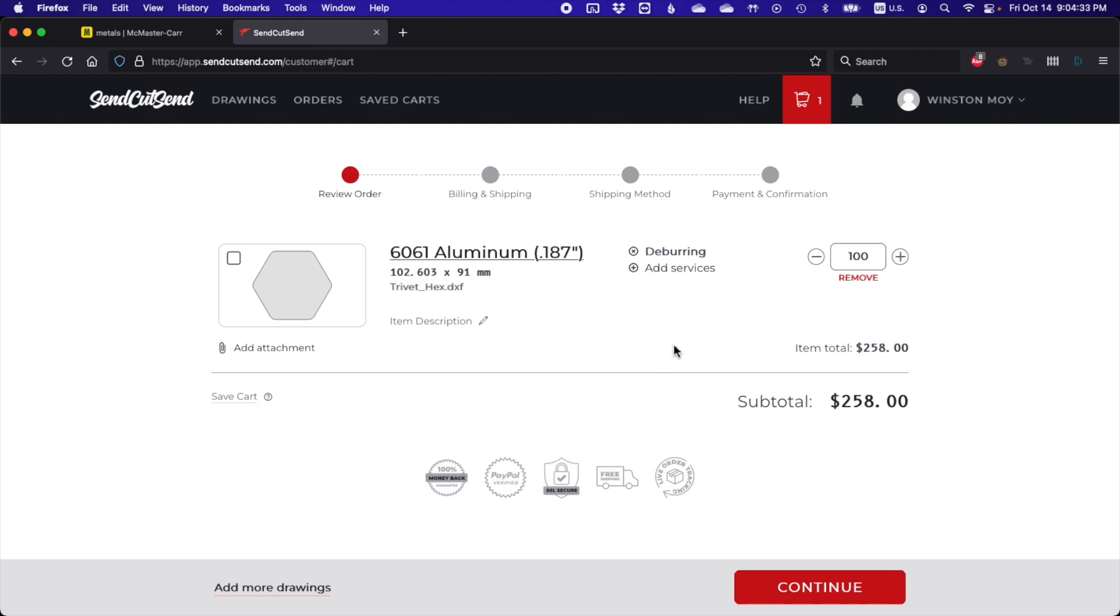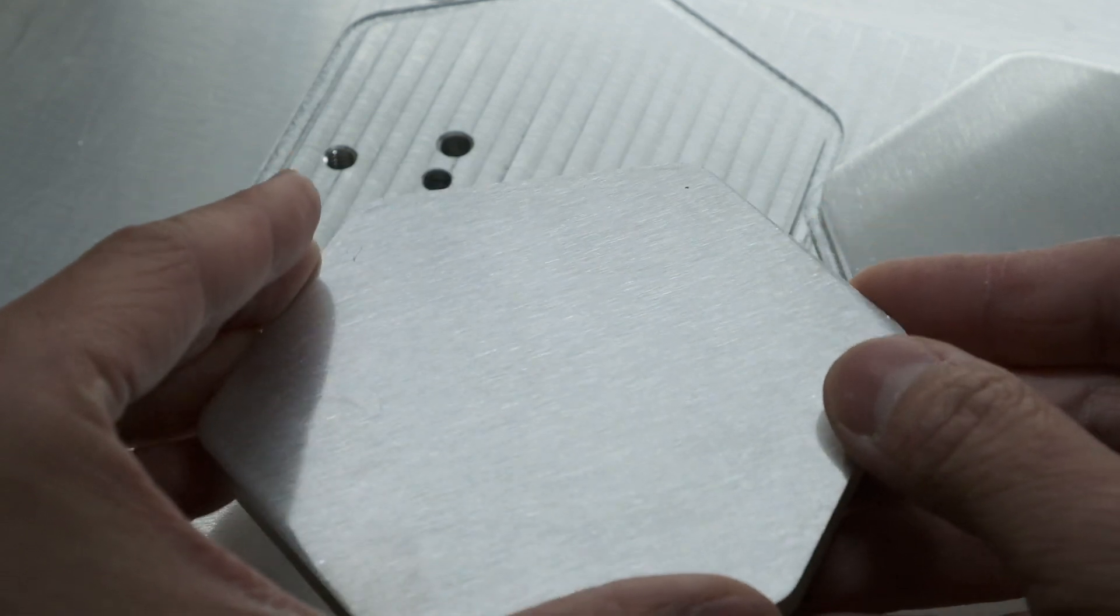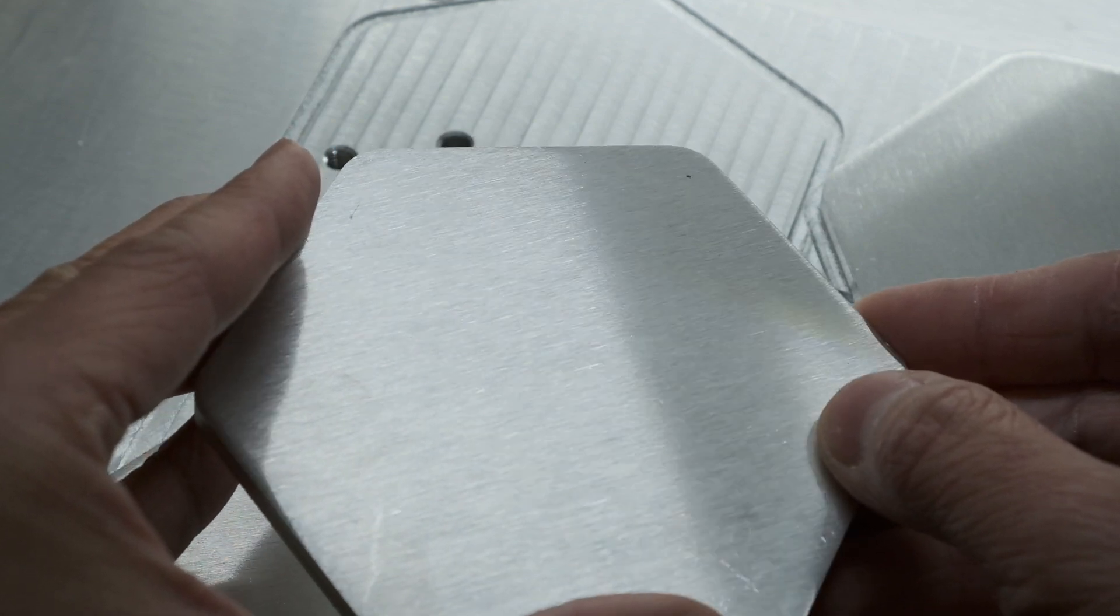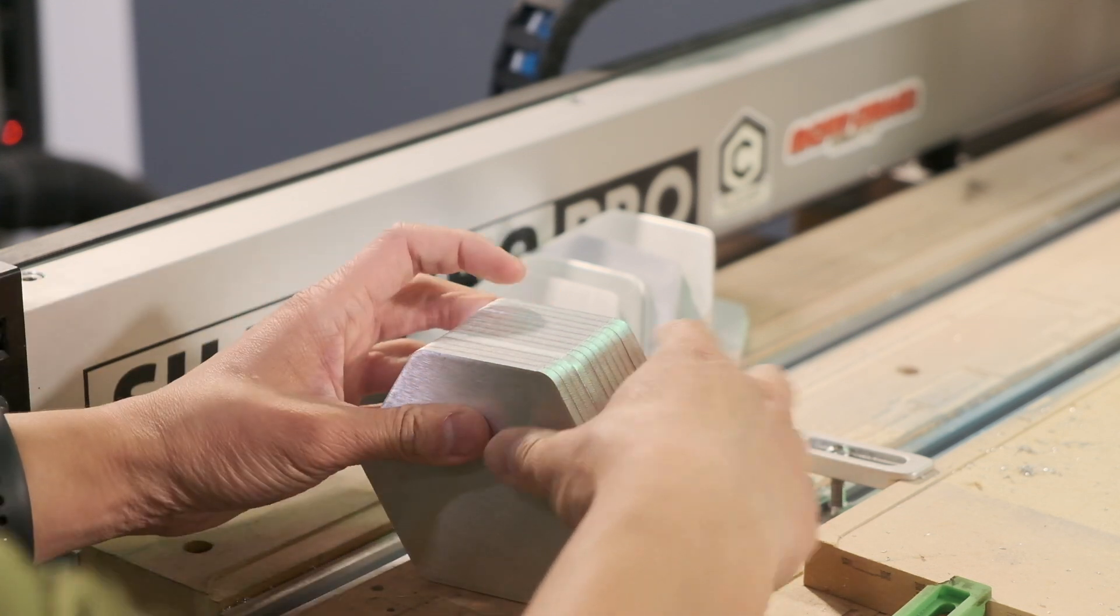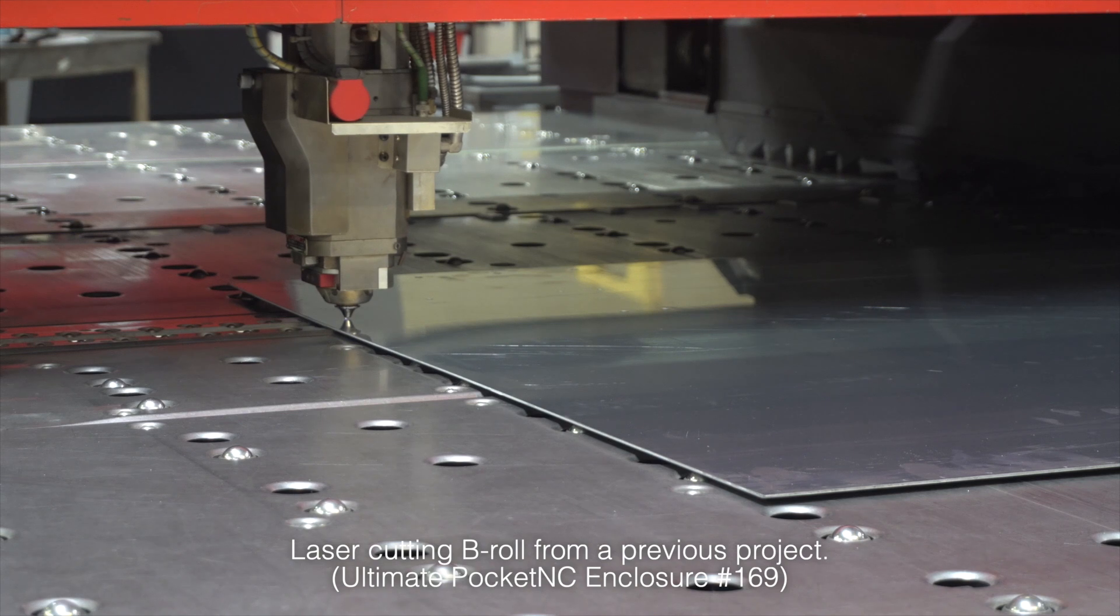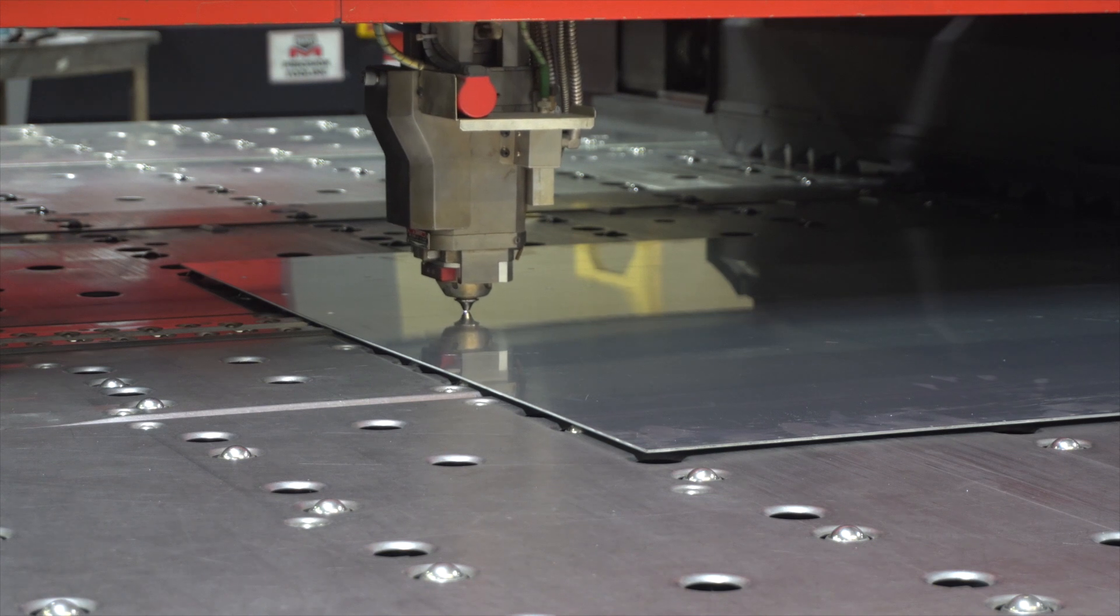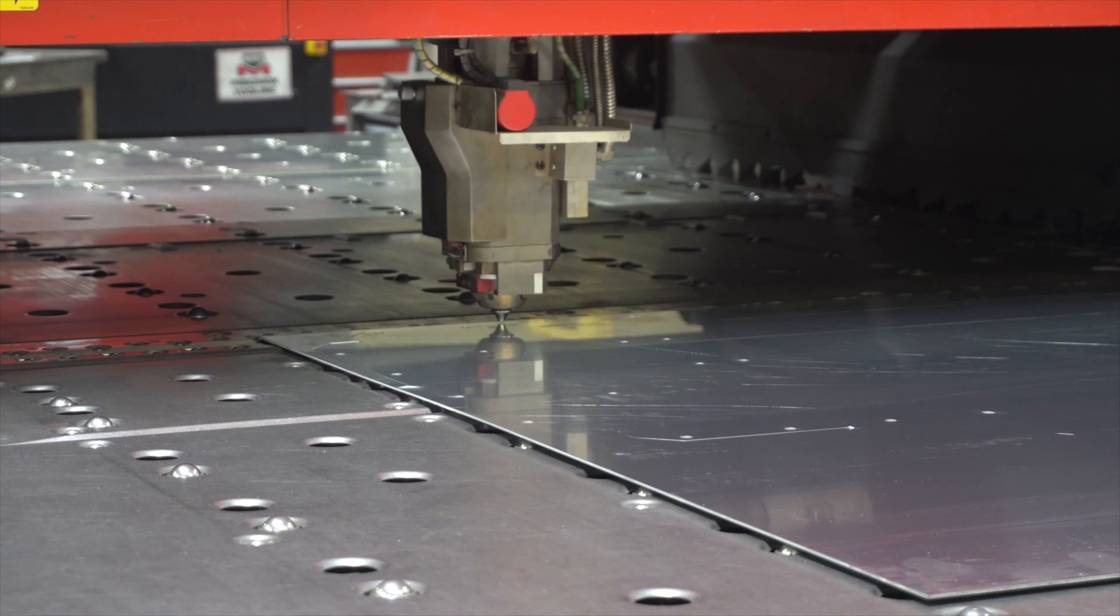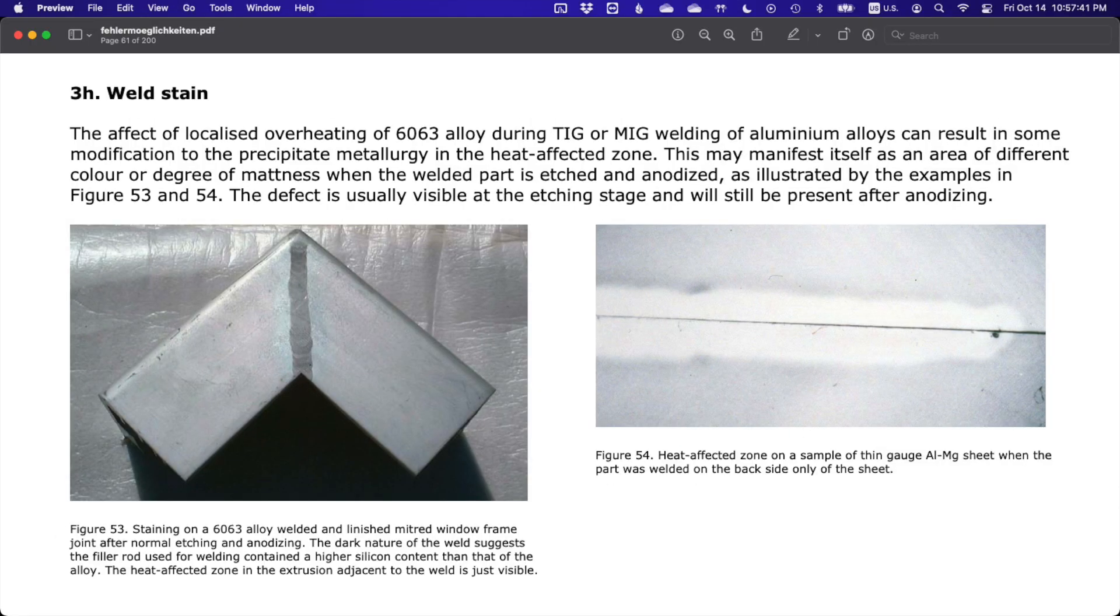I will point out that there are a couple things you might want to keep in mind when using laser-cut parts like this, and these are not specific to SendCutSend. Number one, if your parts are deburred for you, the edges will often end up slightly beveled. Two, there will often be an entry artifact on the perimeter where the laser starts and stops cutting. You can grind this off or deal with it on the CNC later. Three, if you're going to anodize laser cut parts, you need to consider the heat affected zone. The thermal energy from laser cutting can alter the crystalline structure of metals and oxidize the material adjacent to the kerf. When you grow an oxide layer on top of this, which is what anodizing is, it can look visually distinct from the neighboring material. This is much more pronounced in processes like welding and plasma cutting, which pump way more energy into the metal, but it's still something to consider here.